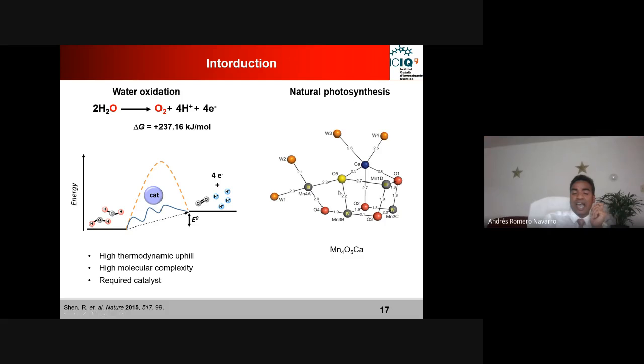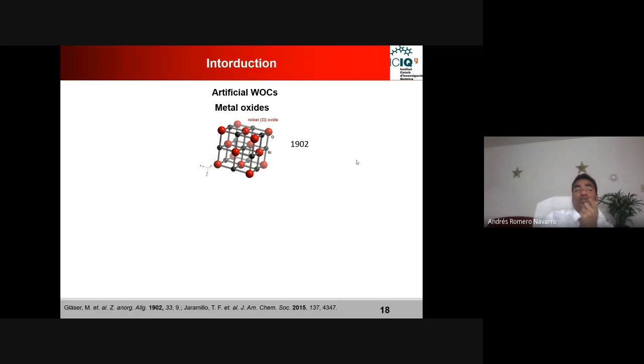Nature has this catalyst called the manganese calcium cluster, where all the oxygen atoms of this cluster are connected with the metal, and 4 water molecules in the periphery complete the coordination sphere of this catalyst. And it has an activity, or turnover frequency, of between 300 to 400 per second. So people got inspiration from nature: okay, nature has this catalyst, so can we design some kind of artificial catalyst that can mimic this transformation? So yes, people tried to design artificial water oxidation catalysts.